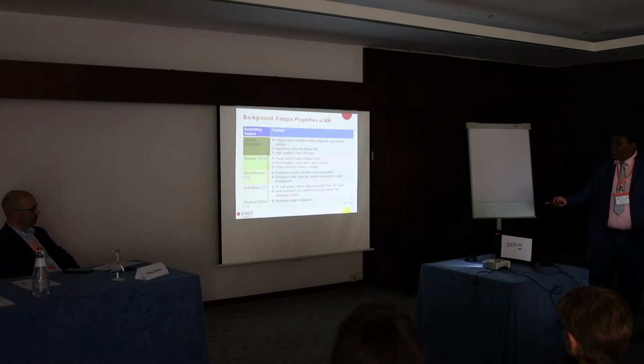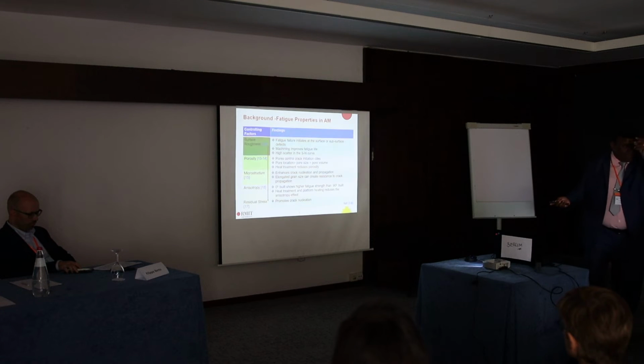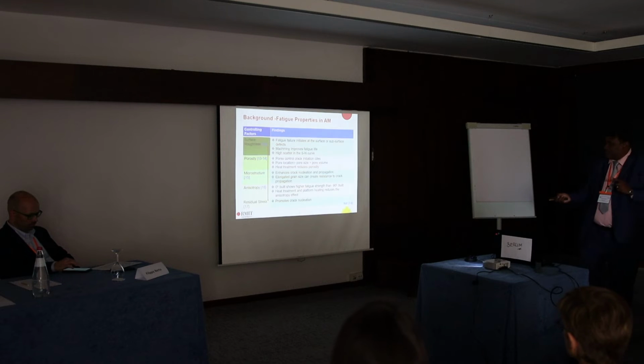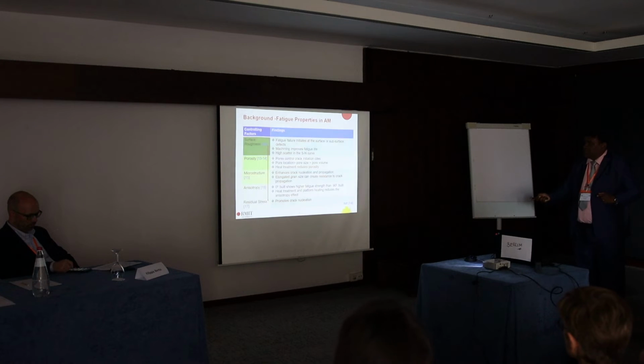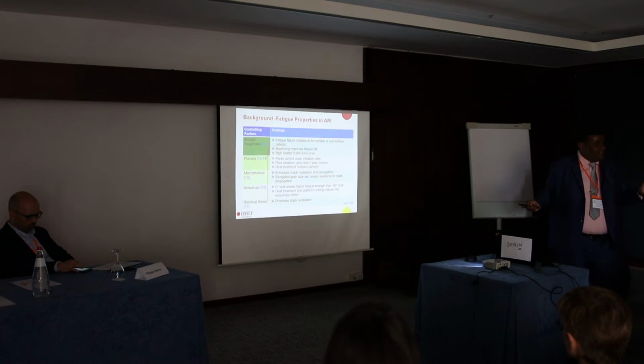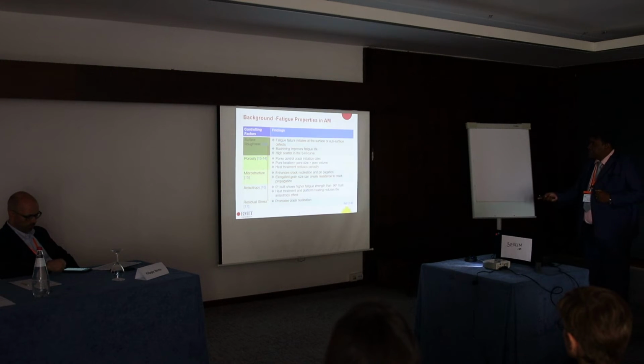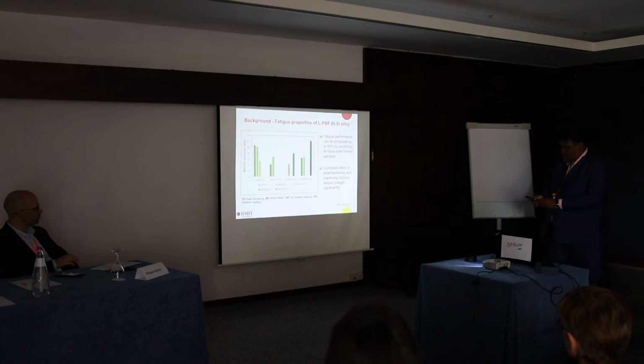The microstructure enhances crack nucleation and propagation, and obviously by controlling the grain structure with the build direction, we can control crack resistance within the material. So we have to understand that, but that effect is less than porosity. And finally, of course, in additive manufacturing we have 0, 90, 45 builds, which will introduce anisotropy. And finally, the residual stress. Now with that,